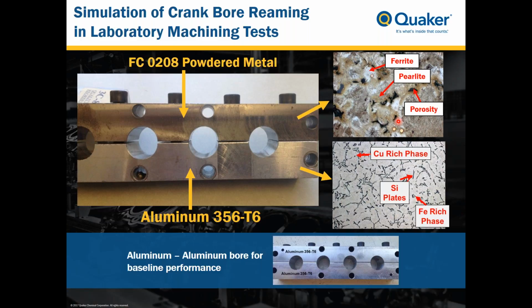To be able to demonstrate the difficulty in bimetal machining, we also wanted to study and test what is the machinability of a part that's not bimetallic. So for this, we also fabricated a part that was based on a bottom half of aluminum and a top part that was aluminum. And you can see this in the picture. Again, for this we used aluminum 356 for the bottom half of the bore, and the same metal, aluminum 356, for the top part of the crank bore.